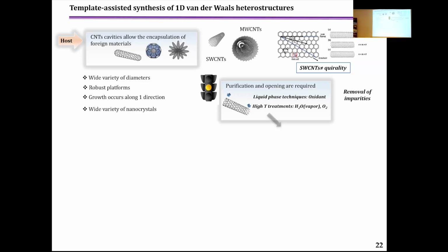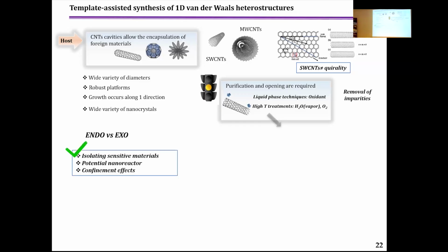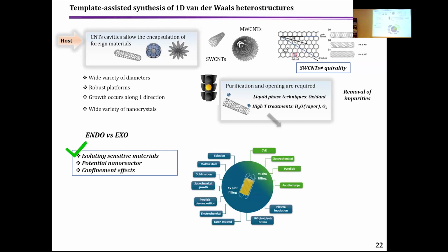which can affect the properties. So the advantage between the endohedral versus exohedral functionalization is that it allows isolating sensitive materials, which usually are damaged by contact with air. Carbon nanotubes can act as potential nanoreactors, and confinement effects can also improve the properties. So we have two different confinement effects: the confinement of electrons along the direction of nanotubes, but also the confinement of the crystal inside the surface of carbon nanotubes.